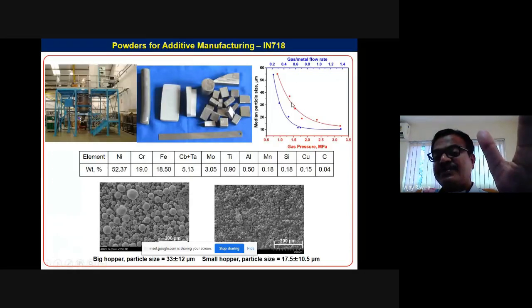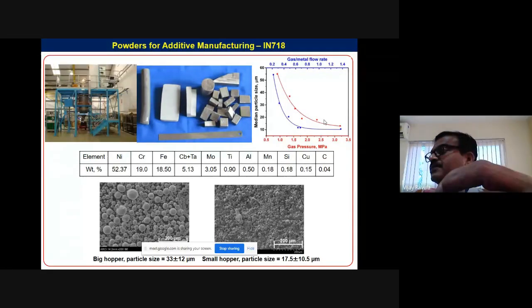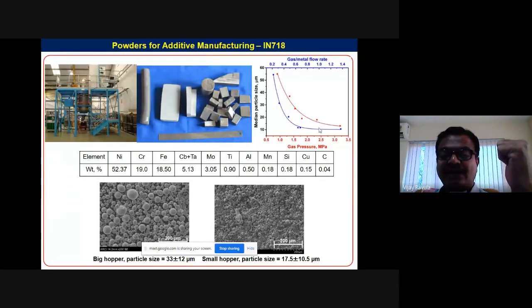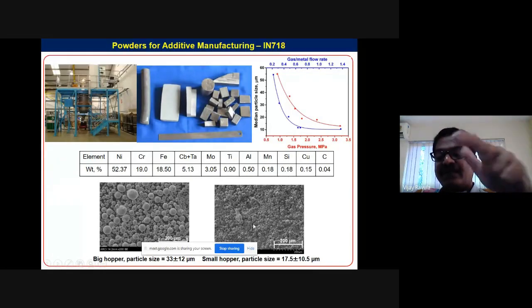Over a period of time we have generated the data, and this graph is produced by making different parameters, and we could see the mean size. Now for any material we can look at what condition we need to get the particle size. Typically, for the powders being produced, we have a big hopper where we got around 33 microns, and in the small hopper we got around 17.5 microns. And typically the 33 microns goes for additive manufacturing.